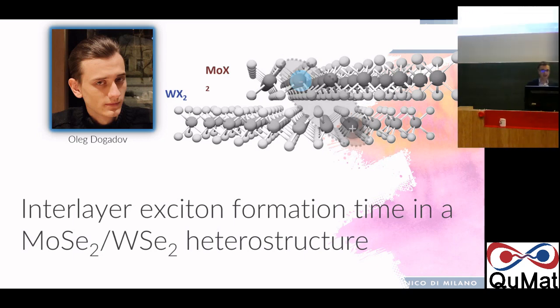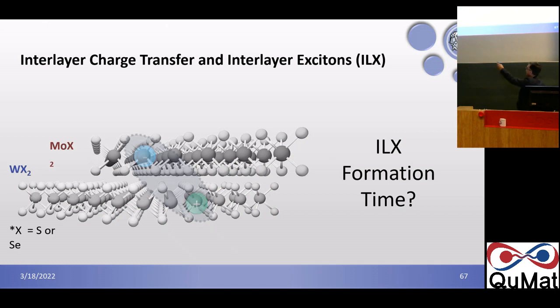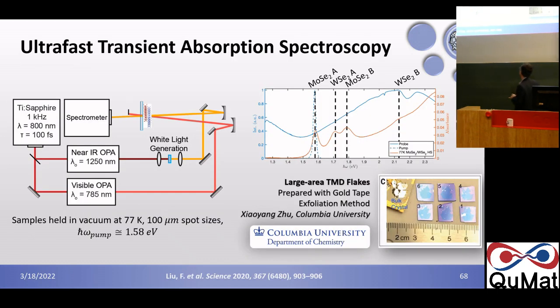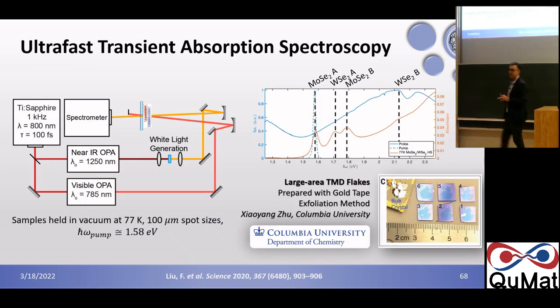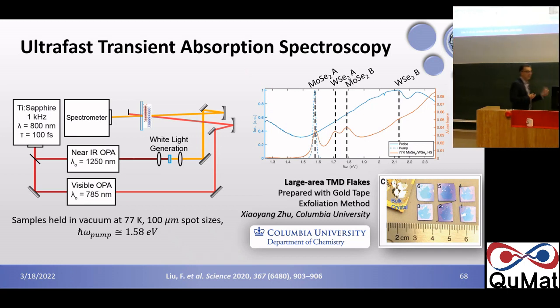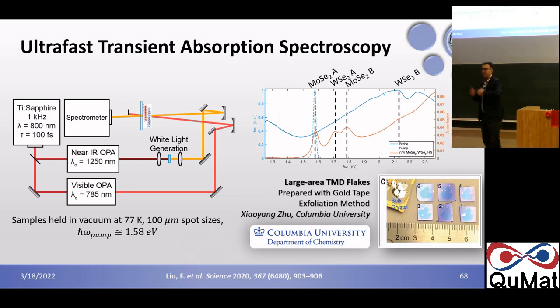Now, after these initial experiments, the question is, what is the time it really takes for this interlayer exciton to form? And now we had a dramatic improvement in the quality of our sample, thanks to a collaboration with Xiaoyang Zhu at Columbia University, who introduced a gold tape exfoliation method, and it can now produce really large area flakes of single layer materials. Before we had like 10 micron heterostructures. Now we have heterostructures on the order of millimeters squared. So this makes our life much easier.